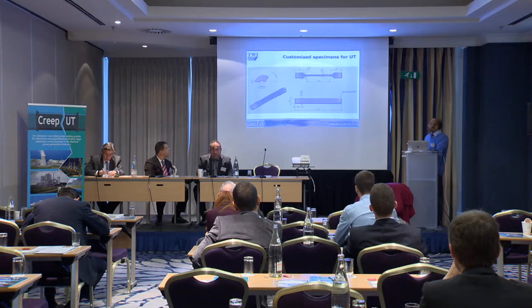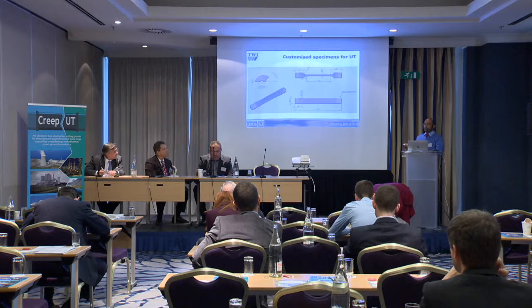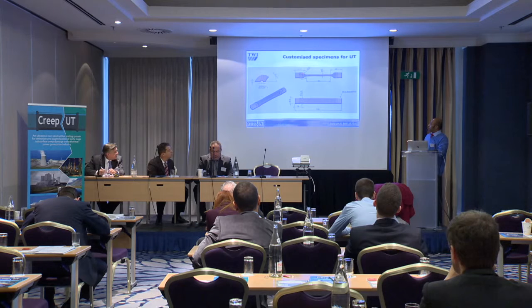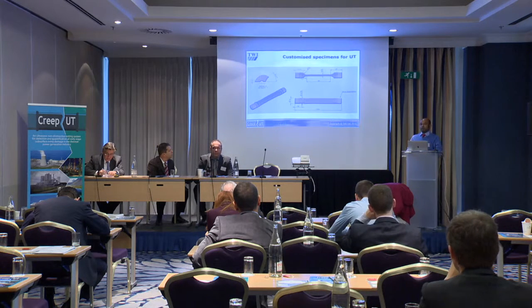And the kind of specimens we also looked at derive from the standardized creep test specimens, which are essentially circular. But what we have is essentially specimens that were flat, so that the UT calibration and testing aspects could be implemented more easily. So there were lots of issues, like, for instance, the need to create this radius, because otherwise you have areas of sharp stress risers.